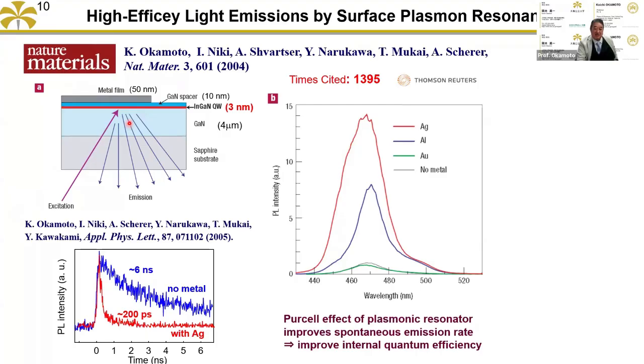Then we obtain the light emission from the backside. We can obtain more than 10 times enhancement using silver, and also some enhancement with aluminum, and no enhancement using gold. And we also find that it's not only the intensity, but it also enhances the spontaneous emission rate. The lifetime becomes very short. That's a very important thing.